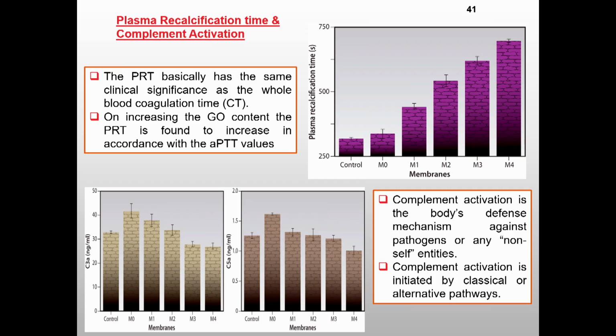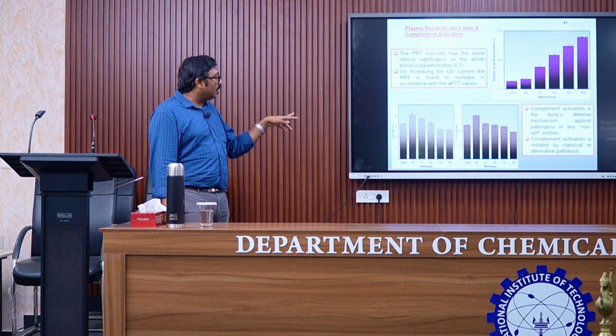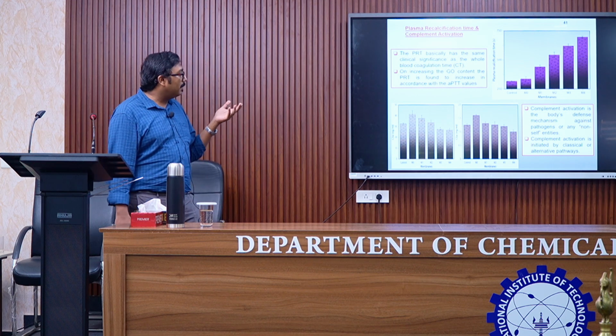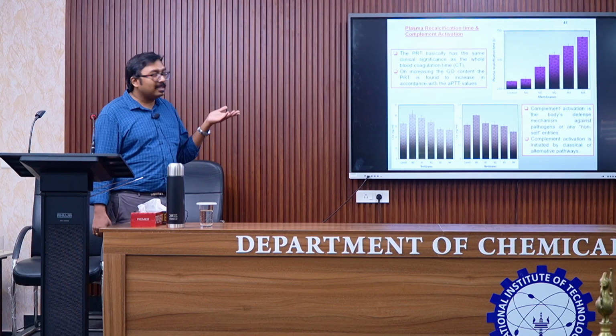There are different pathways for complement activation, direct or indirect. Again, I'm not going into detail on that. But we would like to see that the membranes M0 in both cases activated these complements, which is undesirable, but the modified membranes were lower than the control, which in a way was good because they make the membrane safer from complement activation.